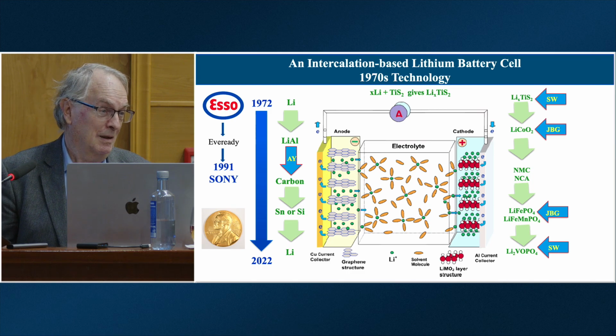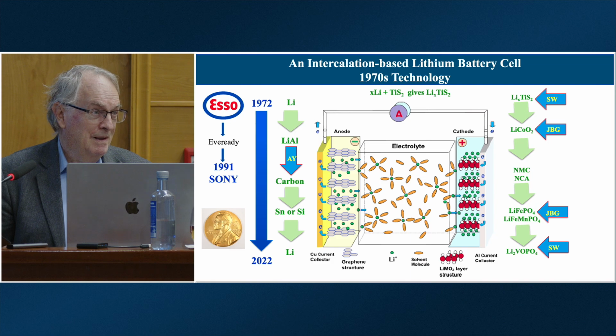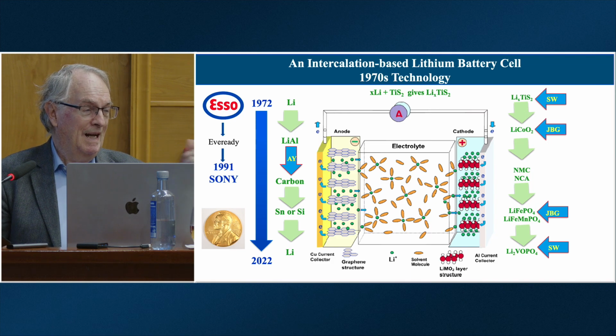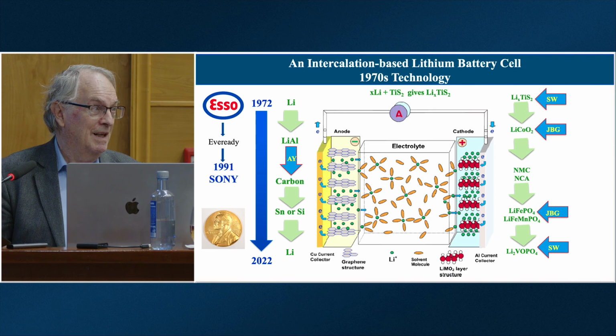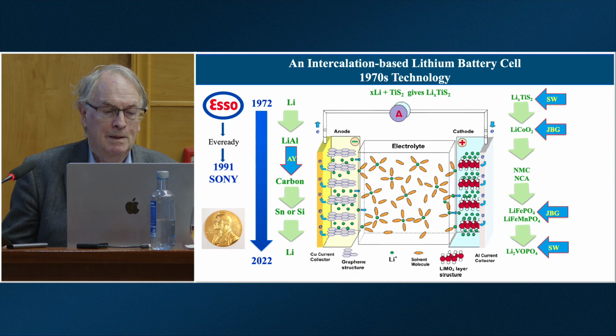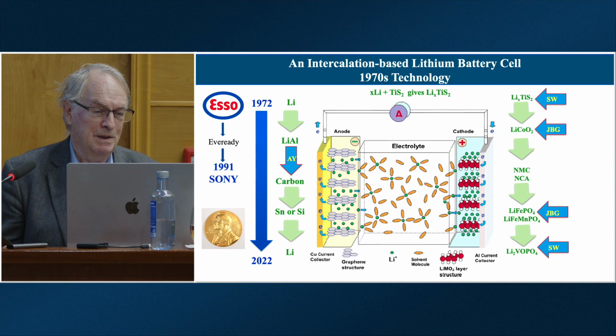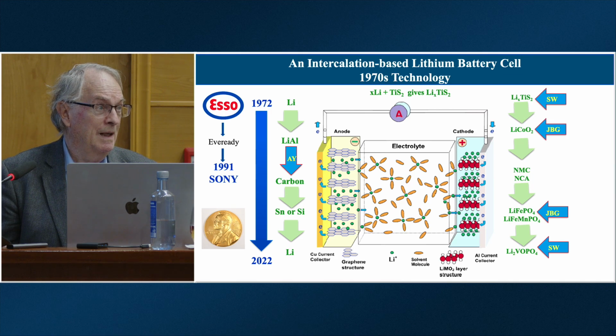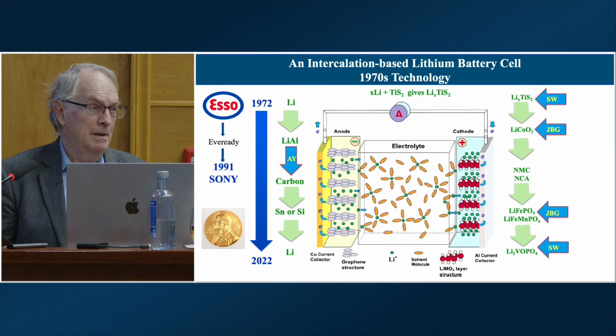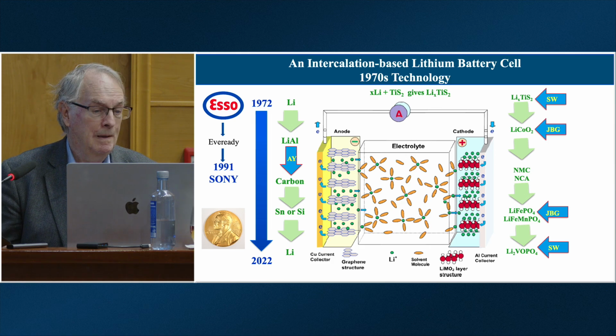It's a metallic conductor. So remember, in the battery, you're putting ions in, you're also putting electrons in or out, so you've got to have conductivity for the electrons. So it had a huge positive effect. It worked very well, but its voltage was about 2 to 2.5 volts. When we then combined that with a graphite anode, that cut it down by about another 0.5 volt.